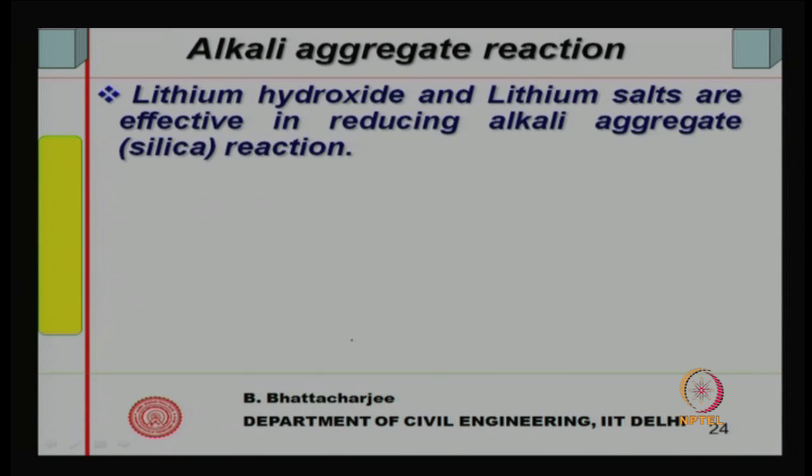Now, these will react with some silica minerals forming alkali silica gel, and this gel can adsorb water and expand in volume, resulting in cracking of concrete. We will again deal with this somewhat later on when we talk of durability of concrete, but there are some inhibitors which can stop this kind of reaction. Of course, you have other means of controlling them, but inhibitors can also be used.